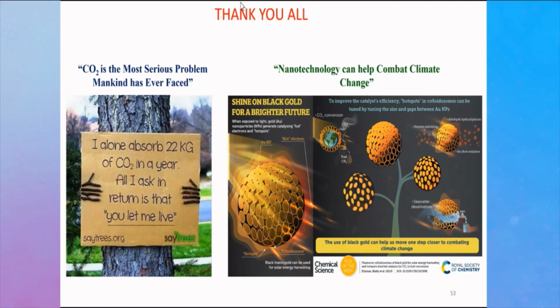Somya Pai asks: my question is regarding the last slide you showed, that 2 micromole per gram of methane forms. So even if you have taken 100 milligram of sample, it becomes 0.2 micromole. By which technique did you measure such a small amount of methane? By GC. That depends on which GC you use. We have a GC which can detect up to 10 ppm of methane, and even less of hydrogen. So by the GC you can detect even very small concentrations of these gases.